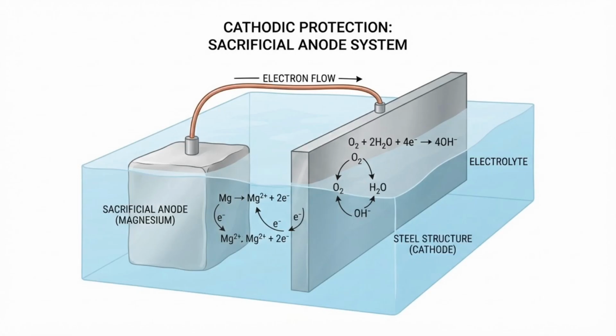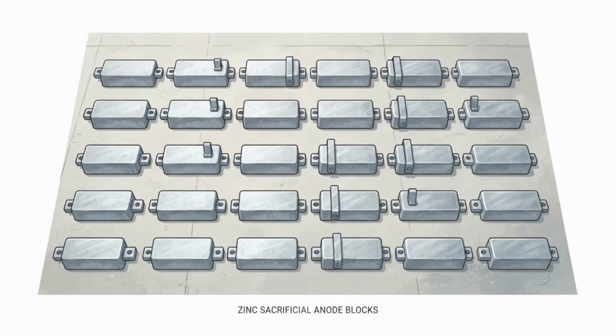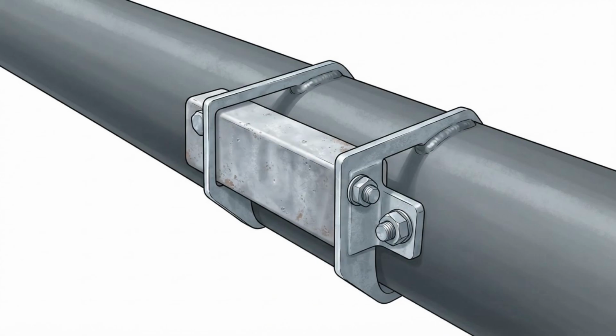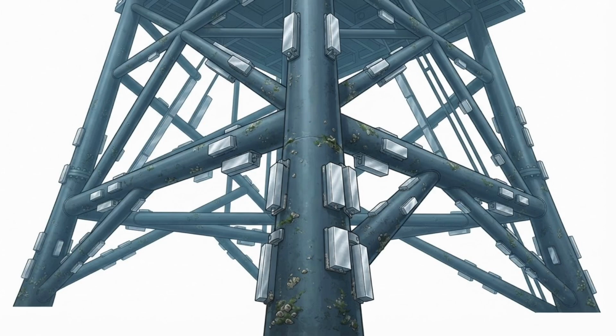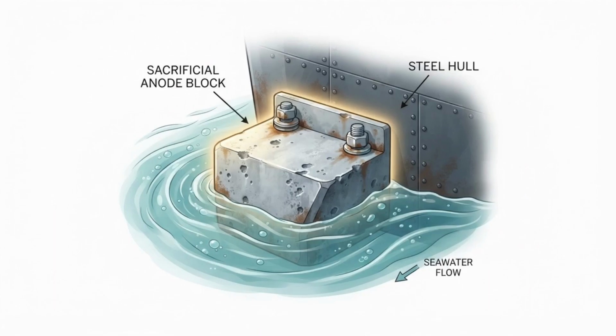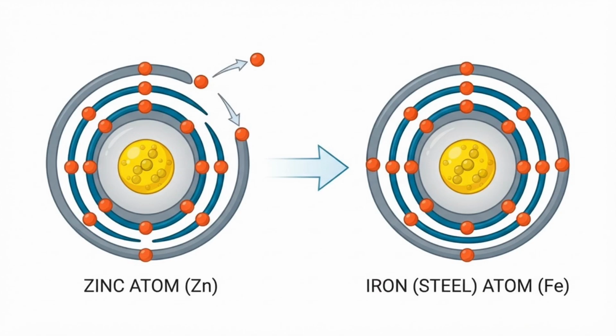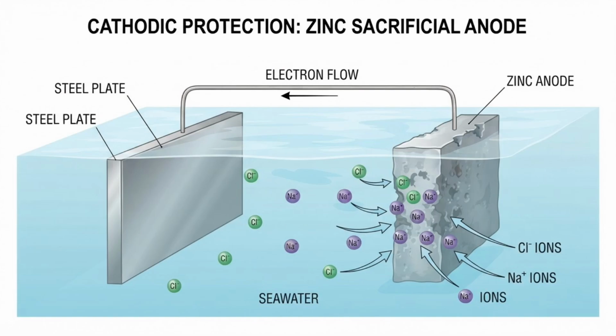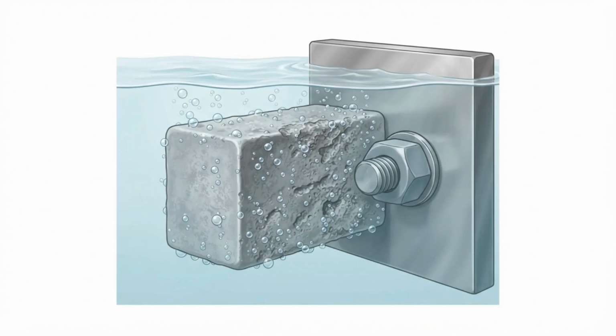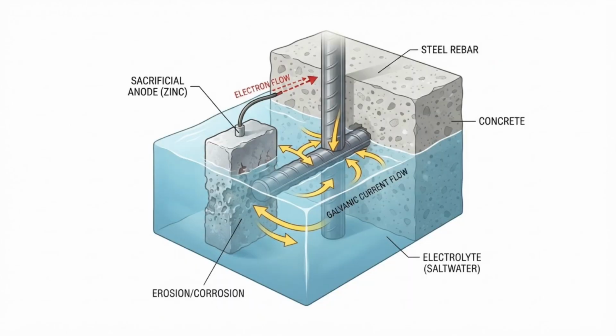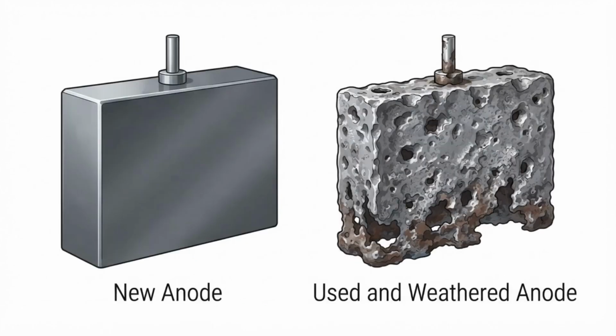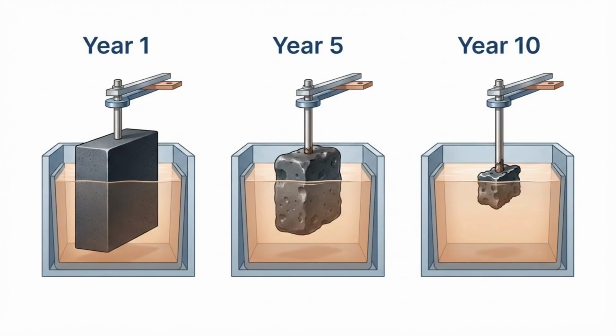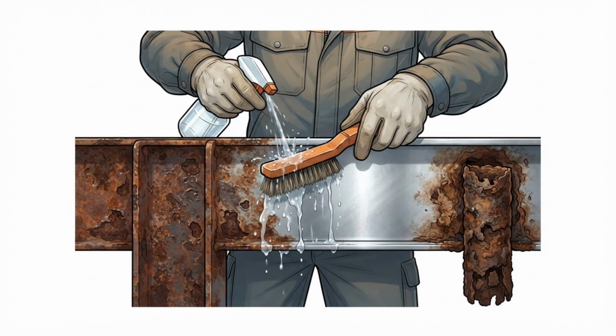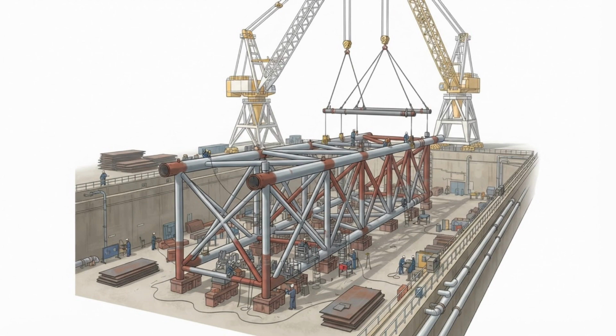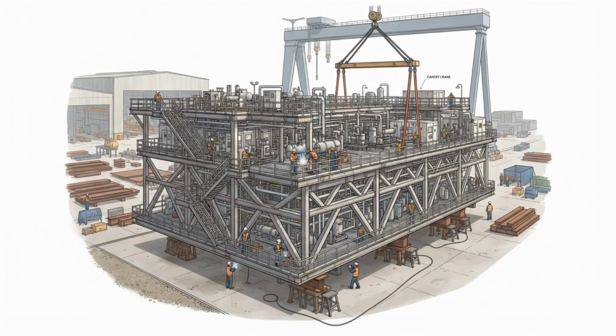To provide a deeper layer of defense, engineers utilize the principles of electrochemistry by attaching hundreds of large blocks made of zinc or aluminum directly to the submerged portions of the steel hull. These blocks serve as galvanic sacrificial anodes. Because zinc and aluminum are more chemically reactive than steel, the corrosive electrochemical reaction of the salt water attacks the anodes instead of the rig's structural framework. The anodes slowly dissolve over many years, sacrificing themselves so the primary steel remains completely pristine.